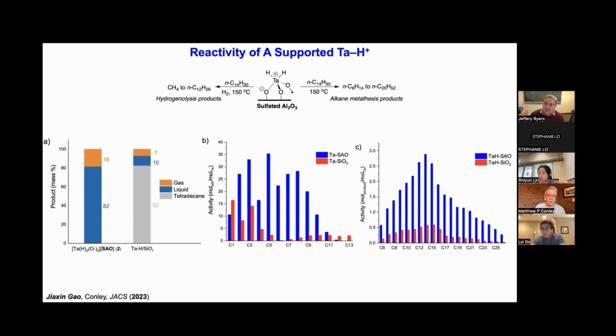No, you're absolutely right. That would be super cool. One of the things we've been focused on is actually trying to control the distribution of products. And I don't think you can actually do it through the hydrogenolysis mechanisms. So we're trying to leverage some of the specific chemistry that tantalum can do, related to alkane metathesis reactivity, to see if we can game this to go one way or the other. We don't have anything yet, but the benefit of working with tantalum over zirconium, where most of the community is, is that it does this alkane metathesis and forms different intermediates, where maybe we can get to something that won't make triptane, but could selectively make propane. If you can selectively make propane, you've just solved a problem, because you can take propane and make propylene pretty easily. Right. But no, thank you for the suggestion. I think those are really great suggestions and things we need to look at with this system.